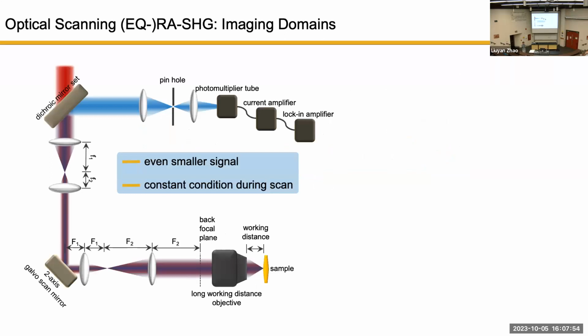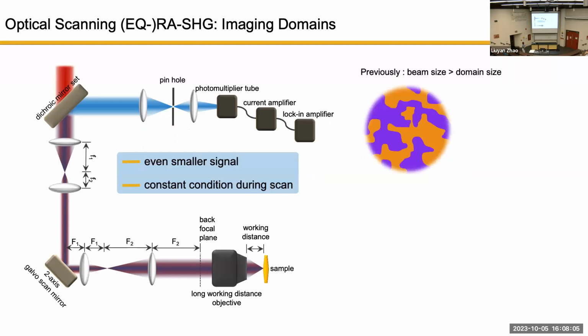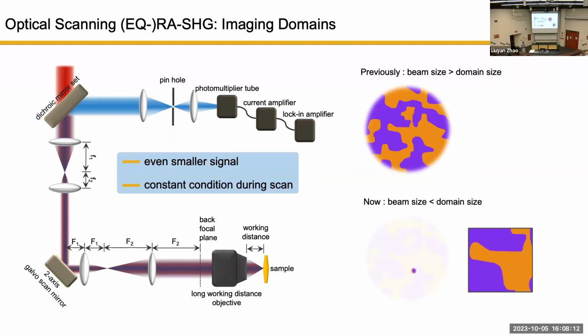So we don't feel very excited, since our beam is big enough to cover both domains. If we want to see individual domain information, it is necessary to shrink down the beam. Better, we can raster the beam across the sample and construct a domain map. But using this big beam, I'm only getting about 15 femtowatt. If I shrink the beam size by 100 times, my signal level is going to go down by 100 times of a weak 15 femtowatt. So we need a technique to make this detection more sensitive.